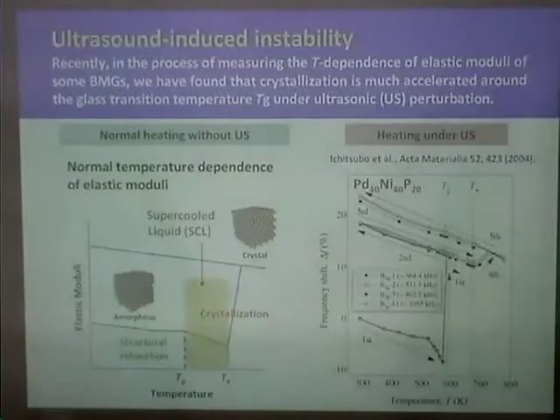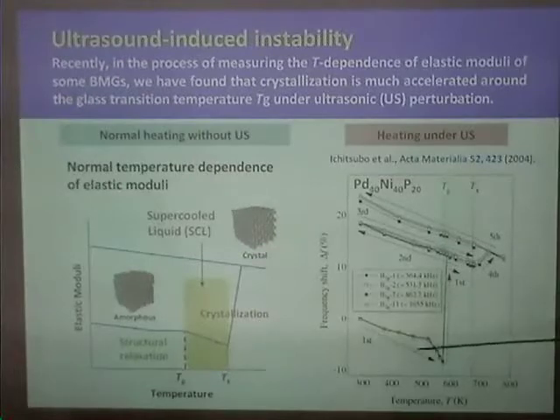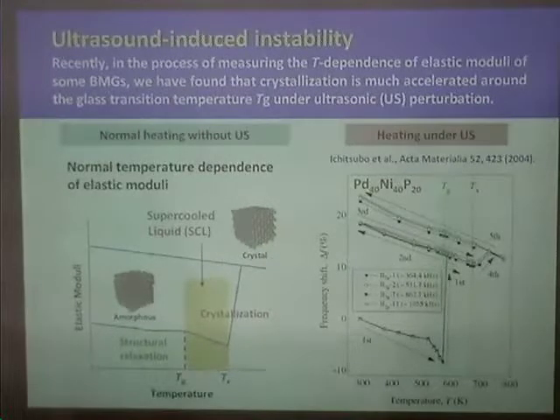But recently, in the process of measuring the temperature dependence of the elastic constants, the elastic constants increased suddenly under the ultrasonic vibration in the megahertz frequency range. So we have found that the rapid increase of the elastic constants around the glass transition temperature, this abrupt increase, is due to the crystallization behavior.